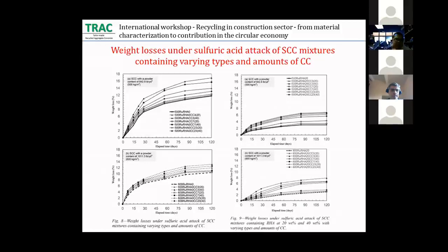Last one, resistance to sulfuric acid attack. In sulfuric acid attack, as shown in the figure, the results of self-compacting concrete mixed with calcium carbonate and rice husk ash over the curing time of testing have a similar trend. The weight loss is high early in the soaking period, and then after 28 days, the weight loss is slightly slower due to the lower reactivity of this indication.